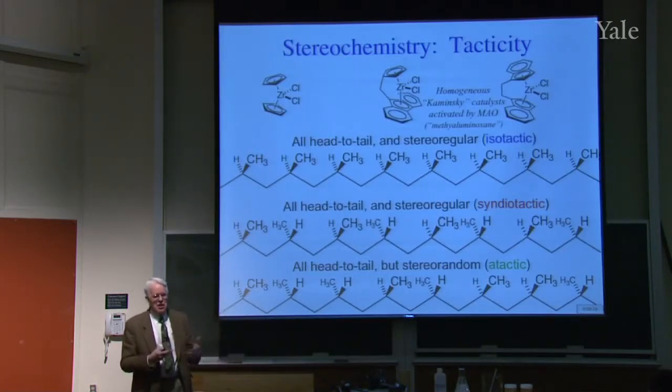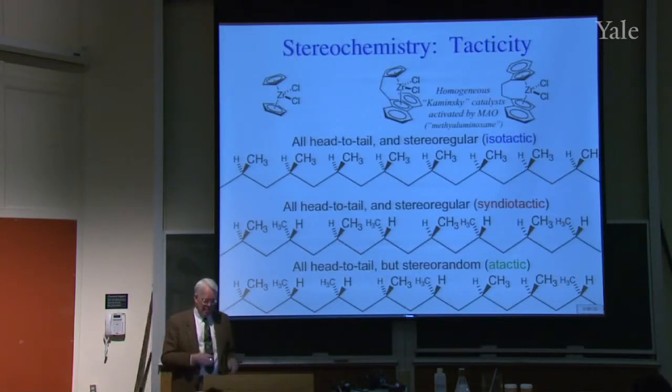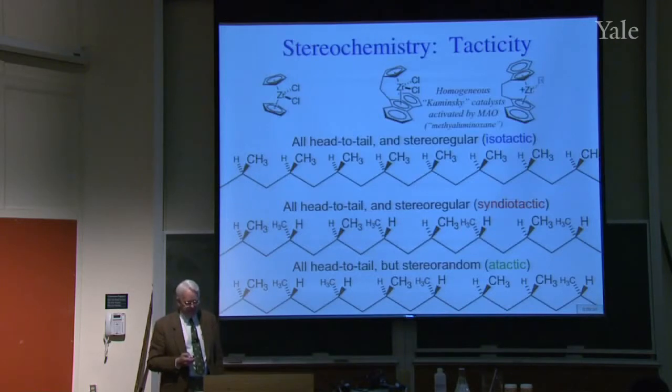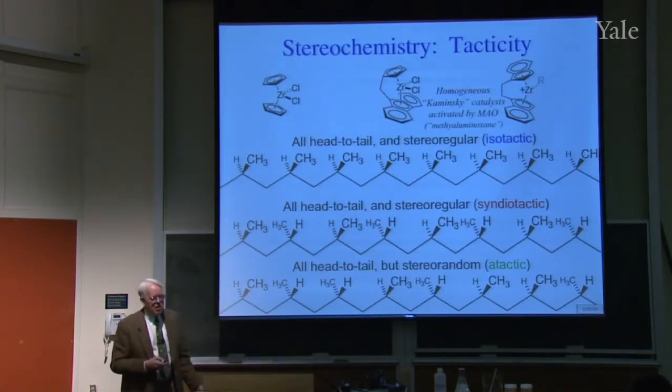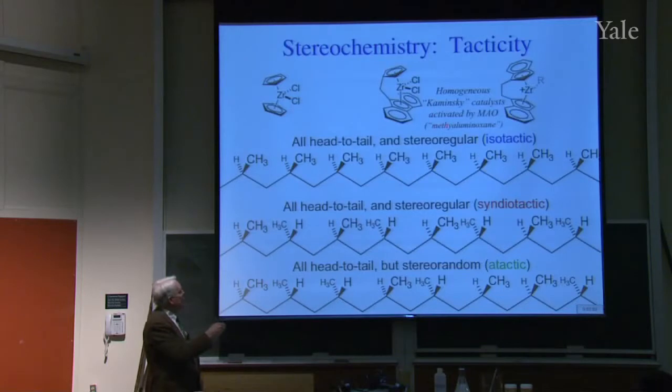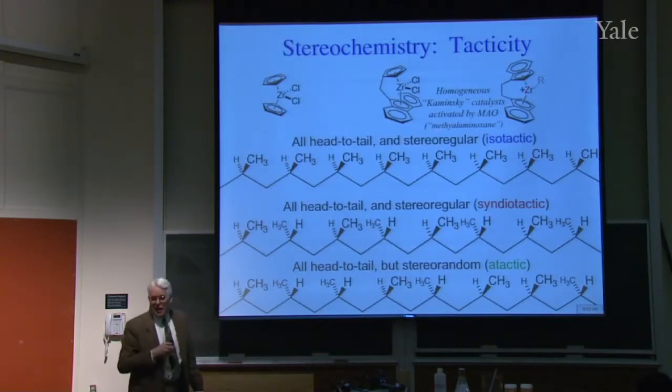Okay? You mix stuff together and you get that. And it's not always the same. But if you add it to these zirconium dichloride complexes, you get a very active catalyst. So since this was discovered in 1980, I think there have been something like 7,000 papers written on it or something like that, and 2,000 patents. Okay. Now, one thing that's pretty much agreed on is that this methyl aluminoxane takes the chlorides off, puts an R group like methyl on the zirconium and leaves it as a cation.